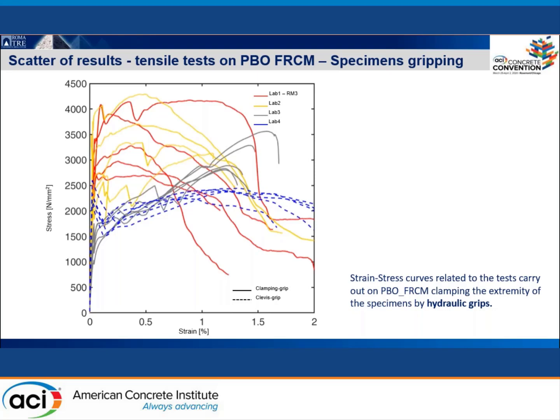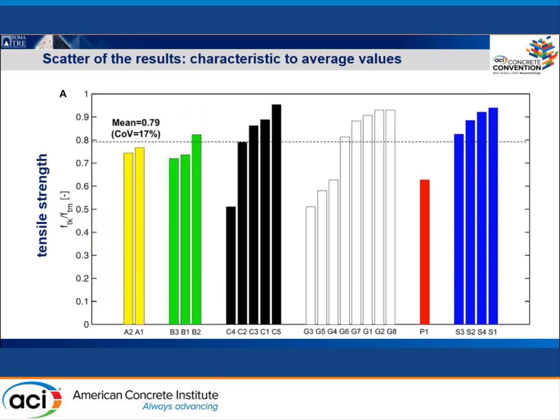And such a wide difference between testing mainly depends on how you grip the specimen. If you use hydraulic grips or not, this will change significantly the experimental results. And not only do you have a wide variability depending on testing apparatus, but even with the same apparatus, you get a very large scatter in the results. As you can see here, in terms of tensile strength, the characteristic tensile strength is about 79% of the average tensile strength.